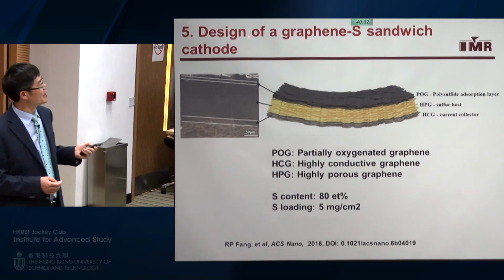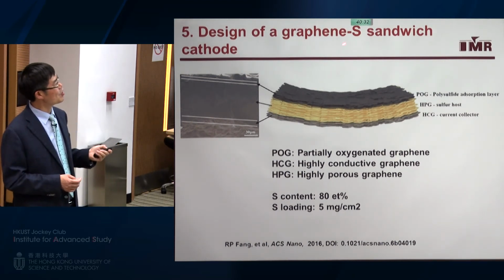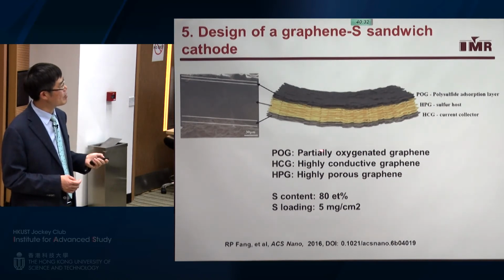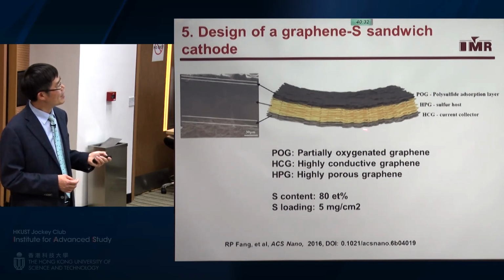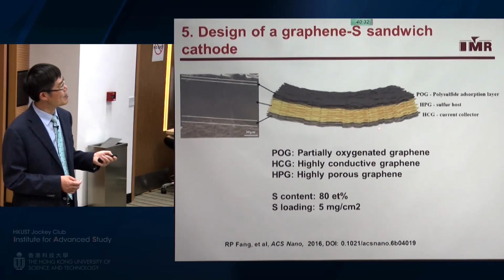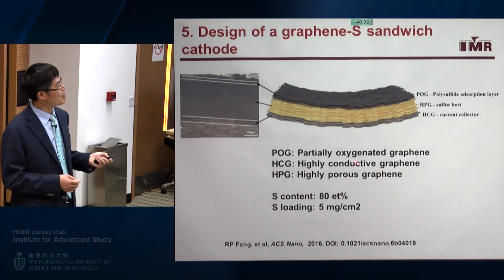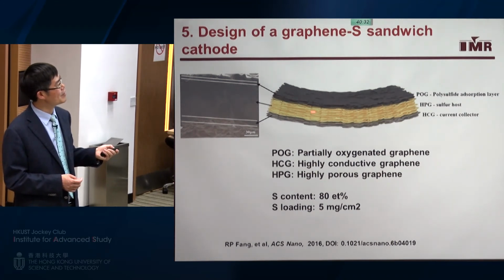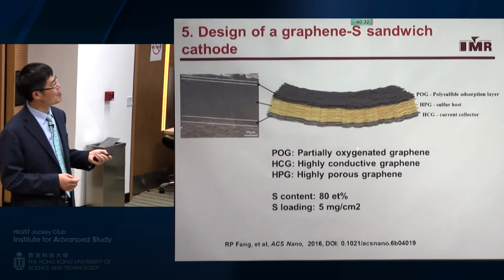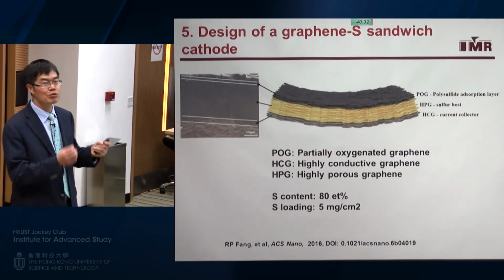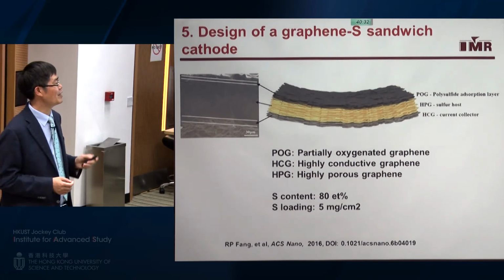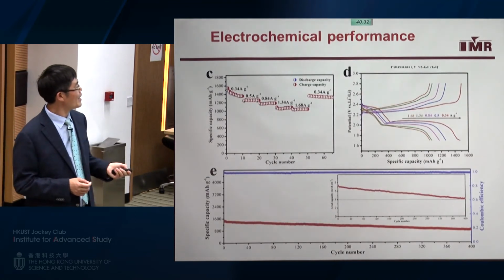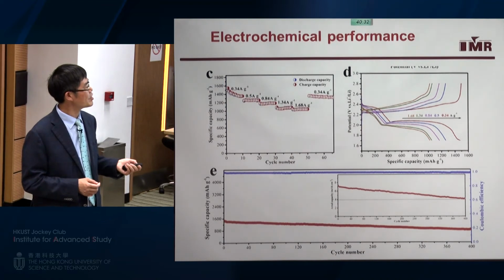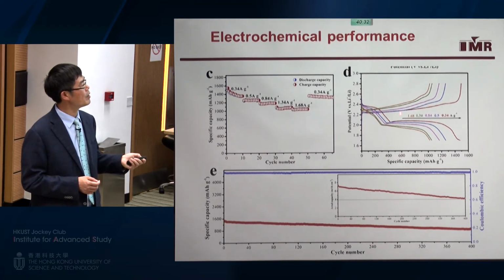And then very recently, we designed this structure. We call it the sandwich structure, because we use three types of graphene: highly conductive graphene, this layer is the current collector; highly porous graphene to host the sulfur active material; and partially oxygenated graphene in this layer to trap lithium polysulfide. So then we also can have very good performance, as I show you here, and a very low polarization.